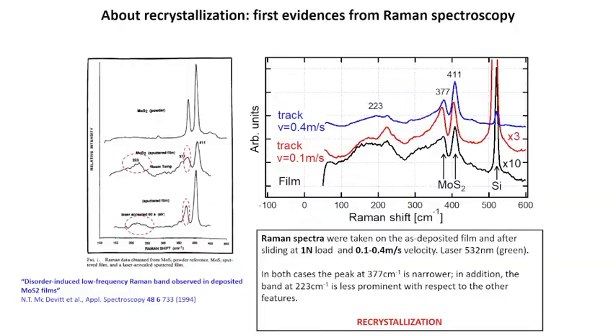Okay, we then wondered what is the role of the ordering of the structure. And in order to do that, we analyzed the coating and the counterbody by means of Raman spectroscopy. In this part of the study, we were inspired by this work here, which has been published by McDevitt and co-workers. They show that here, this is the Raman spectrum related to MoS2 deposited by means of a magnetron sputtering technique. And here you can find the features of MoS2, and in particular, you have to focus on this feature here at 377 in the Raman shift, and on this broad peak at 223.